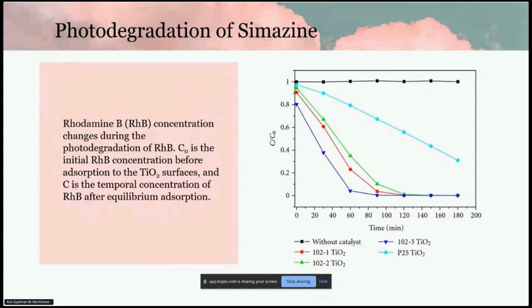The last stage is the Simazine photodegradation under UV light irradiation. This result shows the trend in concentration of rhodamine B over time. As you can see, the concentration of RHB is constant without catalyst, while the concentration of RHB decreases over time using different catalysts.